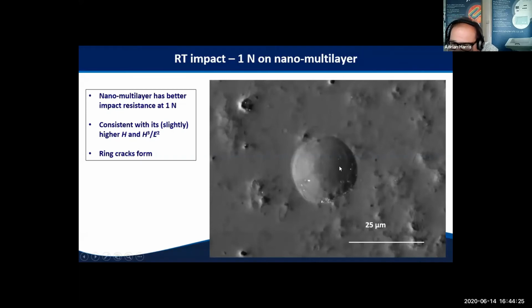When you look very carefully, you can see ring cracks taking place inside the coating itself. Unfortunately I don't have the image in here, but if I compare this with the equivalent on the monolayer coating, we actually had a few radial cracks coming out from the impact site as well. That's a pretty good indicator that this coating is tougher, and that also corresponds with the higher hardness to elastic modulus ratio that we saw from our indentation.